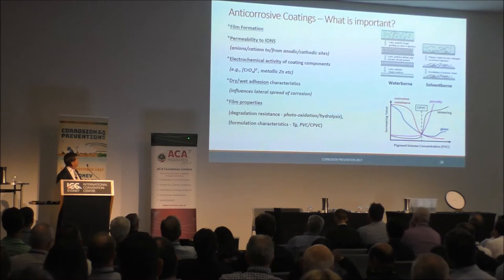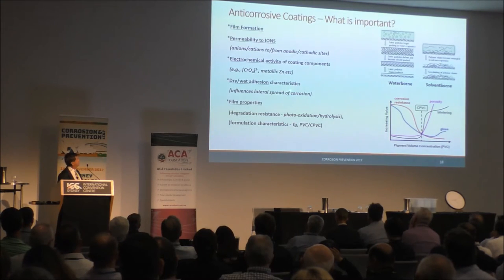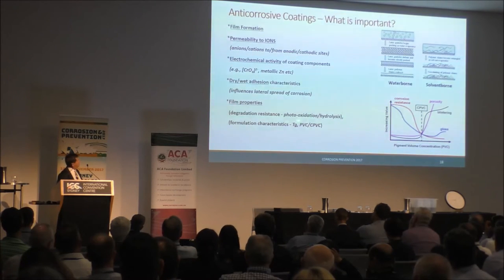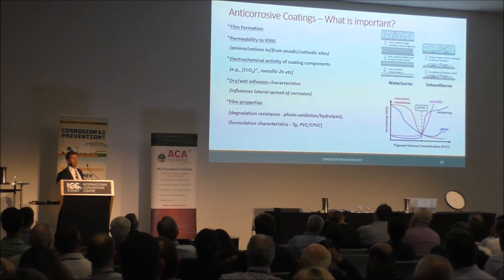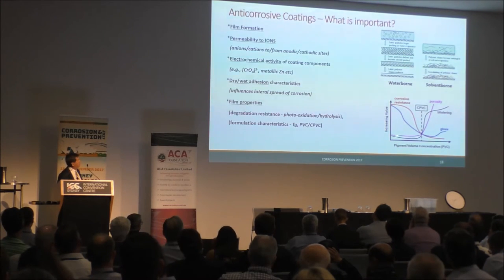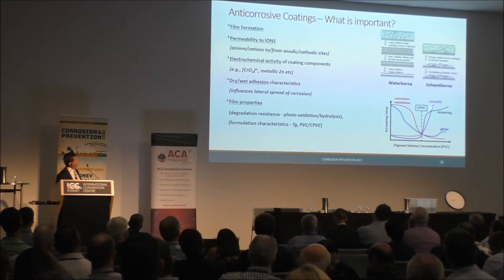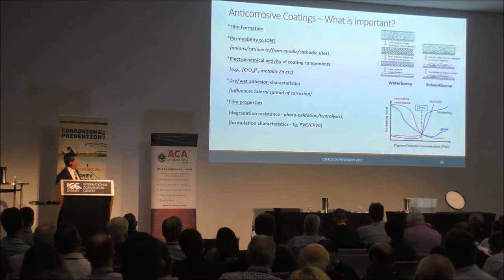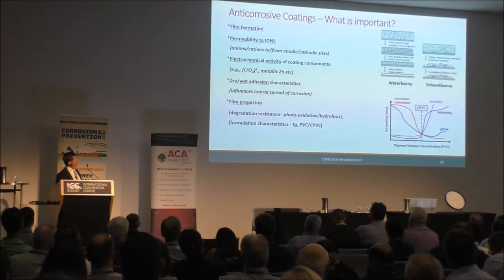But keep in mind that many of these characteristics, dry and wet adhesion, also influence the overall performance levels of the coatings. When you put the coating together, we talk about film properties, and it's very significant how much pigment you put in for the amount of resin. We often look at what's called the pigment volume concentration level. As a function of increasing pigment level, we see a massive difference in the overall performance characteristics of a given formulation. So there is the critical pigment volume concentration, where there's only just enough resin to surround the entire pigment particles that you have in the formula.